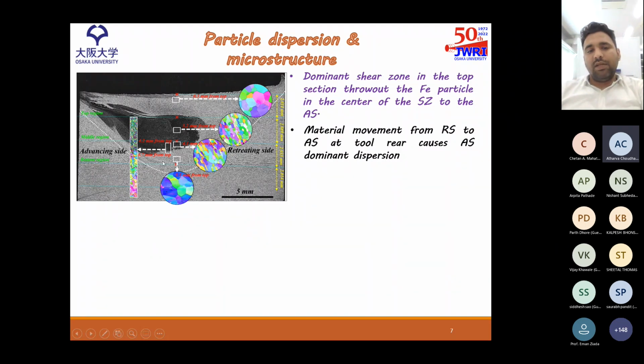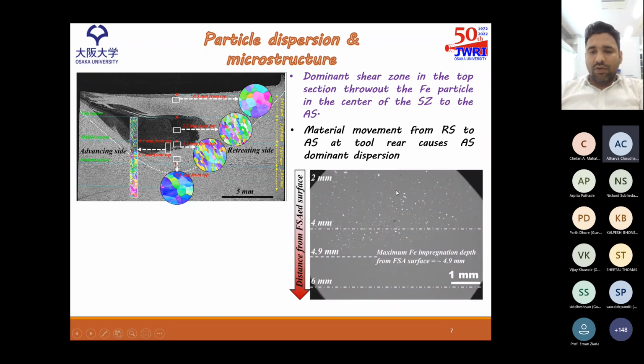Whereas in the middle and the bottom layer, this shear zone is much less dominant, and it does not significantly affect the particle dispersion, and that's why the particles remain mostly in the stir zone only. Now we have also observed this high magnification SEM micrograph. We can see that in the middle region, these white particles are the iron particles. These are homogeneously dispersed, and this is the bottom region.